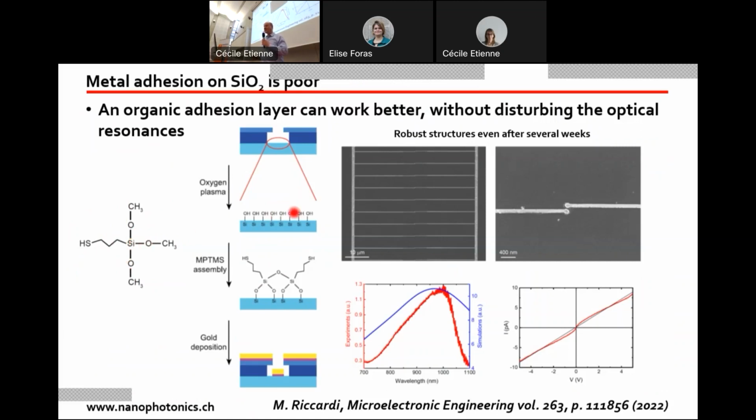So once you put this molecule on contact with the surface, the glass surface, this silicon atom or silane group is going to attach to the atoms of silicon that you have in the glass. It makes these so-called silane bridges between the two. And this is very, very solid. It will not detach from the glass. And this here with the thiol, with the sulfur atom, is going to attach very well to the gold.